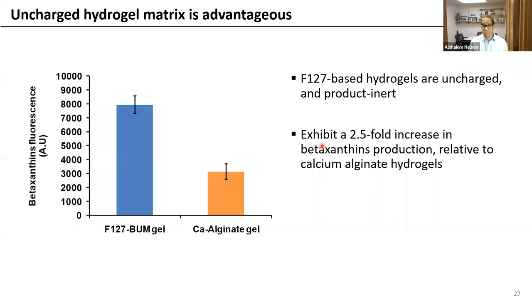And that may be what we're seeing here, and that we observe higher production of betaxanthins in the F127 gel, but it's not to say that the production is higher, but it could be that a lot of the product is just getting trapped within this charged gel network.